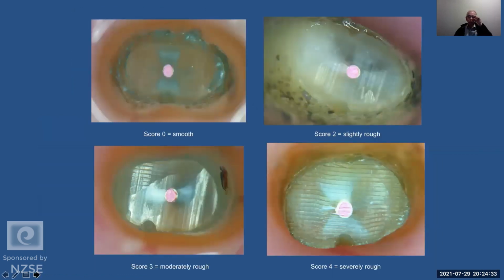And here's some examples here. I think we can all say that that's a severely rough resected root face. This one's moderately rough. And when you look at that, the bevel angles change slightly. So you're almost seeing a crack there when you look at that. And you might record that as a crack. Up there's a beautifully smooth resection. And over here is a resection that we called a slightly rough resection.